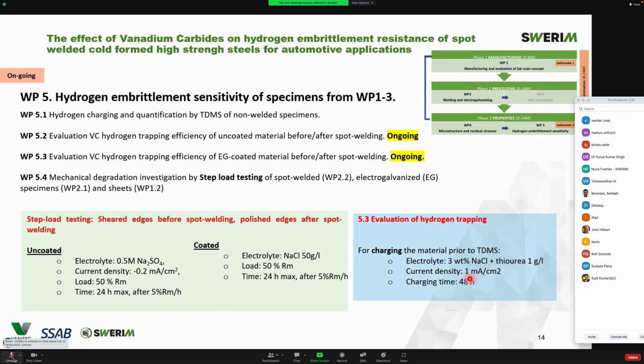As per my experience, because when I was doing work for high carbon material having 1,900 MPa strength high carbon steel wires, we were testing at 70% of the tensile strength. And we found this is happening at very high corrosive conditions.